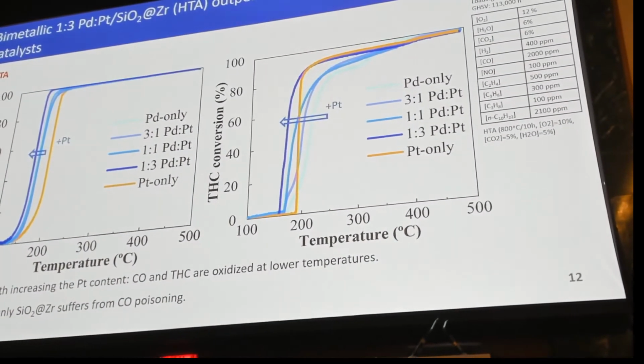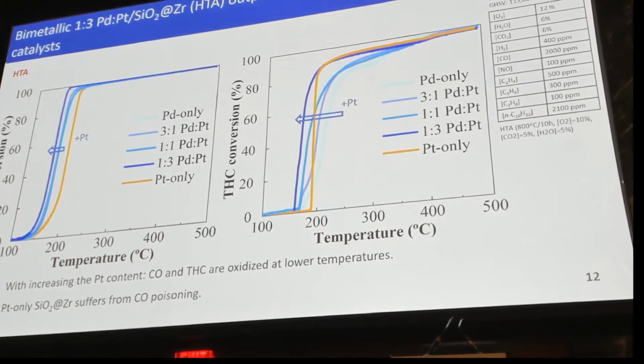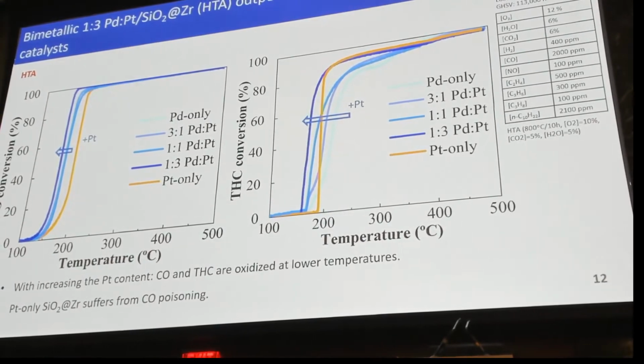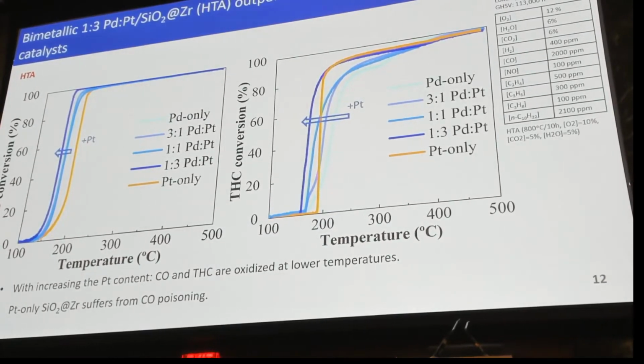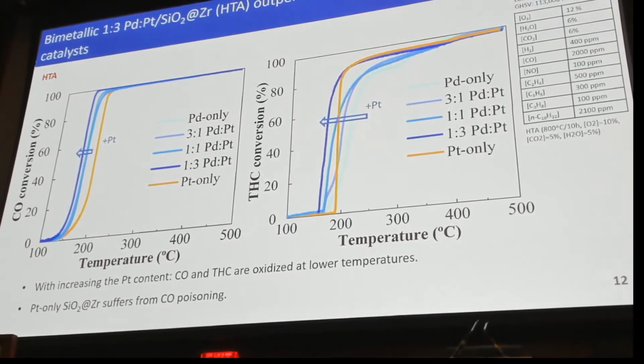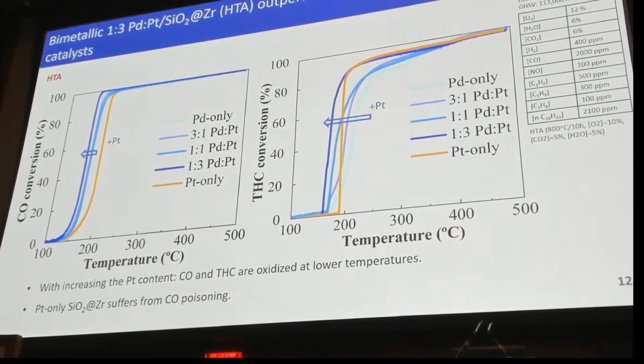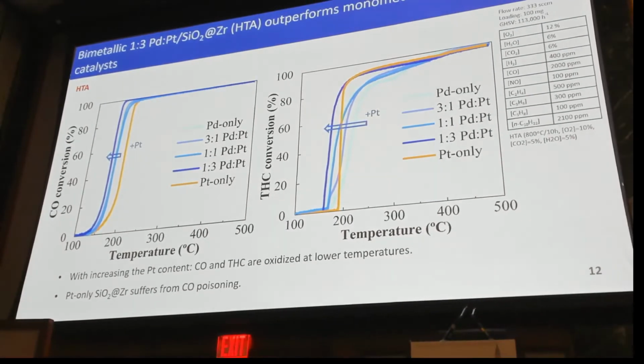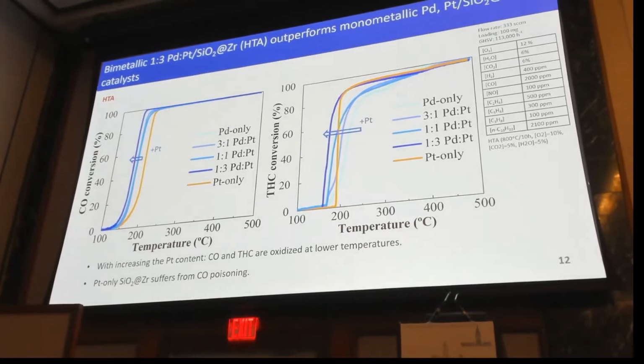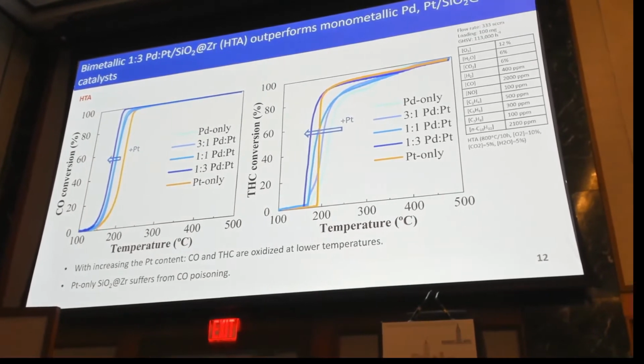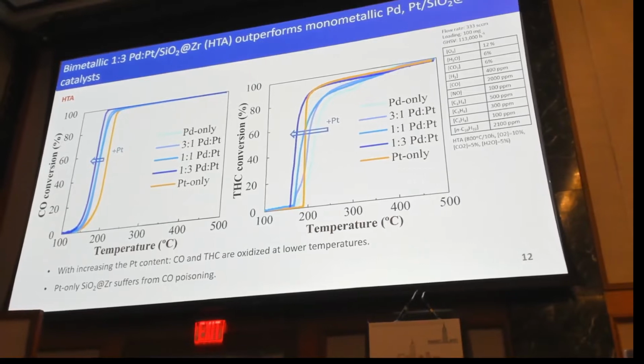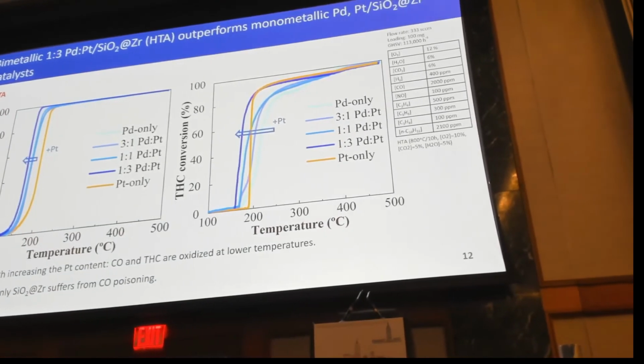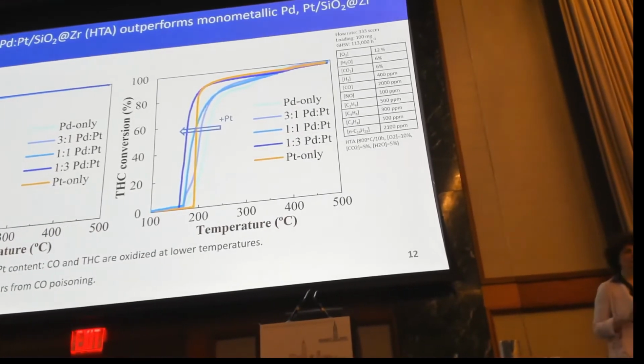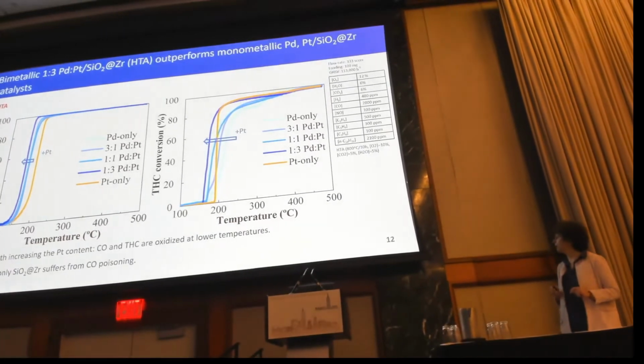So we hydrothermally age the catalyst. And here we can see the performance after hydrothermal aging. Important to note here that there is a small deactivation, but overall the catalysts are very thermally stable. And we see the same pattern. So we see that when we have platinum, the performance improves. And the best catalyst that outperforms all the rest is the one that has 1 to 3 palladium to platinum molar ratio.